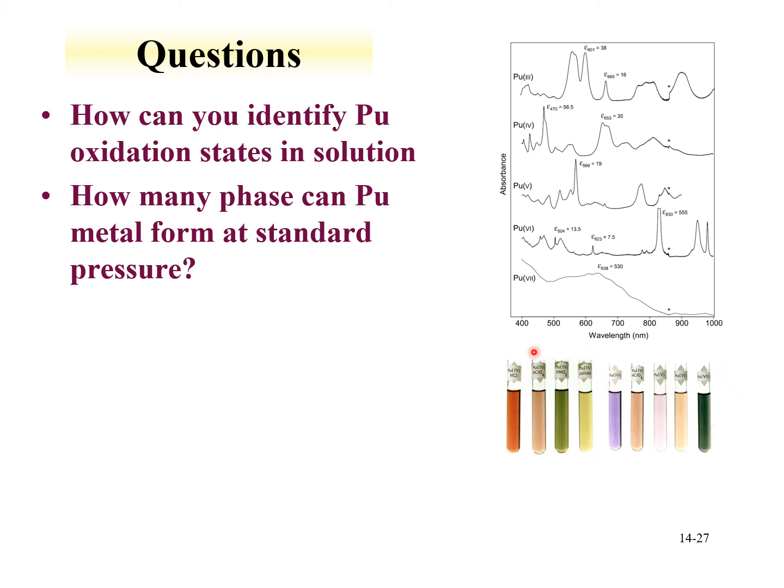We see the different colors. And even for the same oxidation state, here's all tetravalent oxidation states with different ligands, so different acids, HCl, perchloric, nitric, and then plutonium colloid. We see that they're colored, they're visible, so we should be able to use UV visible spectroscopy as a means of determining the oxidation state. And here's the data for the different oxidation states and the peaks with their molar absorptivities.